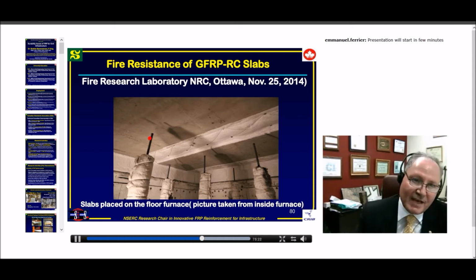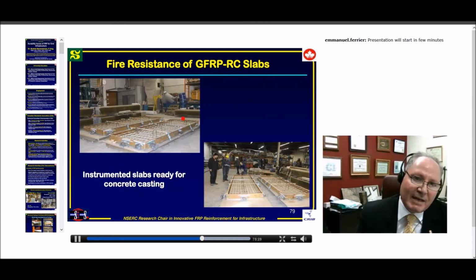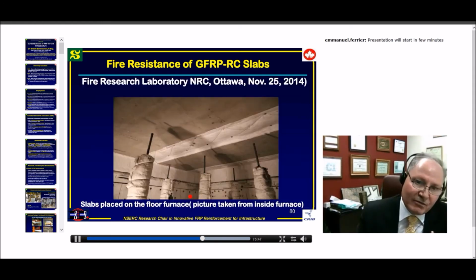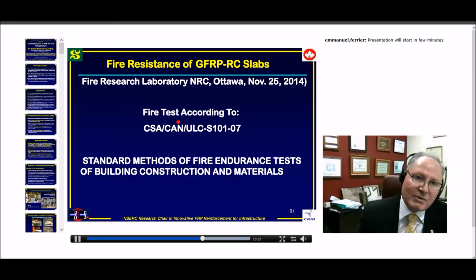You can see the flames will come from this. Let me come back here. When we cast the concrete, we kept the slabs in the lab for 6 months to get the moisture out of the concrete, and then we transported them from Sherbrooke to Ottawa, about 350 kilometers. Then we put them in the test setup in the furnace. We did the fire test according to CSA ULC S101, which is exactly the same as ASTM E119, and the test was done on 25. I can tell you at that time I was extremely stressed